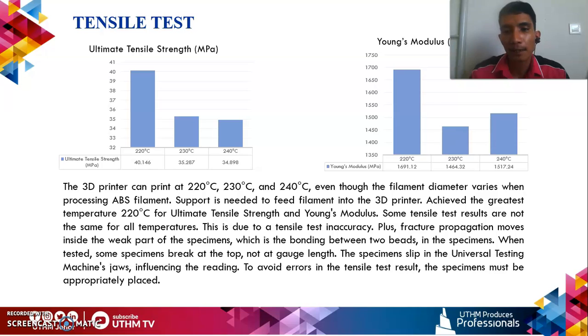The 3D printer can print at 220 Celsius, 230 Celsius, and 240 Celsius, even though the filament diameter varies when processing ABS filament. Support is needed to feed filament into the 3D printer. 220 Celsius achieves the greatest ultimate tensile strength and Young modulus. Some tensile test results are not the same for all temperatures.